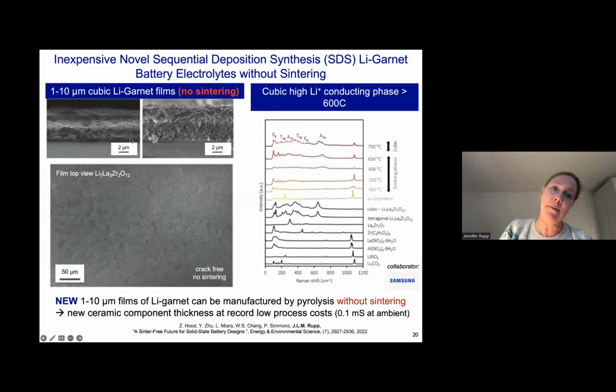You can make films that are between 2 microns and 8 microns in thickness, but they have grains that are just 5 nanometers thin. And we can demonstrate that we hit the lithium garnet phase at around 650 degrees C. So again, where in our PhD experiment we used a post-annealing temperature to hit the high-conducting phase, we're now much lower. In footprint, we use much less energy than in classic sintering, which is much better from the carbon dioxide footprint. And the aspect ratio is also better than sintering, because you have these very small 5 nanometer grains over just a 2 micron cross section, which is almost not achievable with classic sintering.